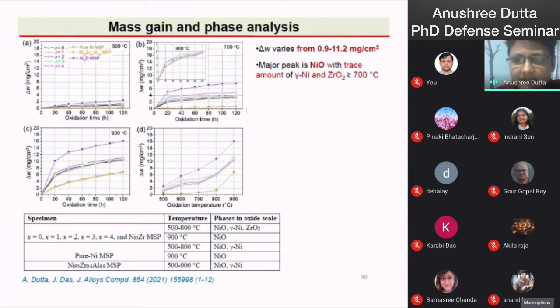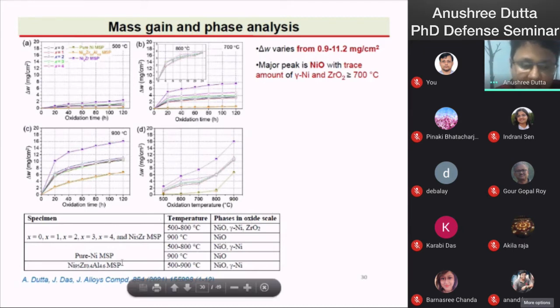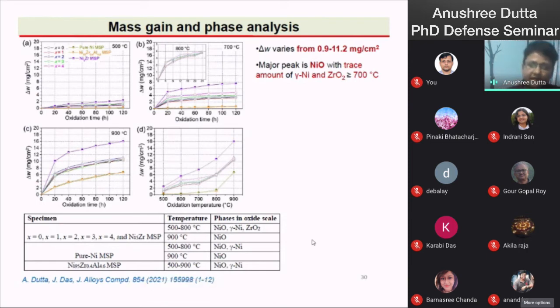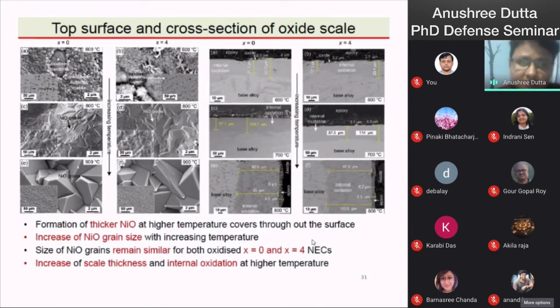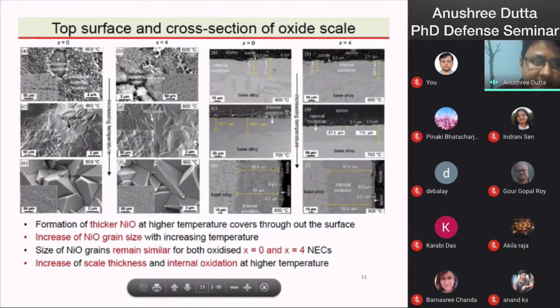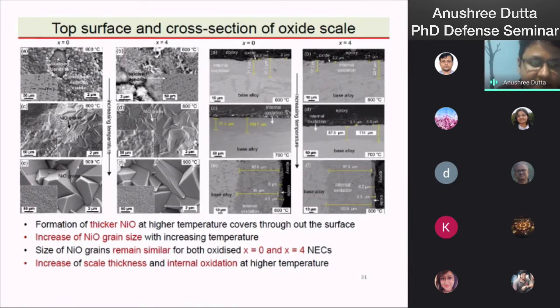The major peaks are NiO with trace amounts of gamma nickel and ZrO2 after 700 degrees centigrade. The oxide phases in the oxide scale are characterized here. In all the cases, the scales are mainly NiO with very trace amounts of ZrO2 and gamma nickel phase. Now this is the top surface and cross section of the oxide scale. On the top surface, we can find the increase of NiO grain size with temperature.